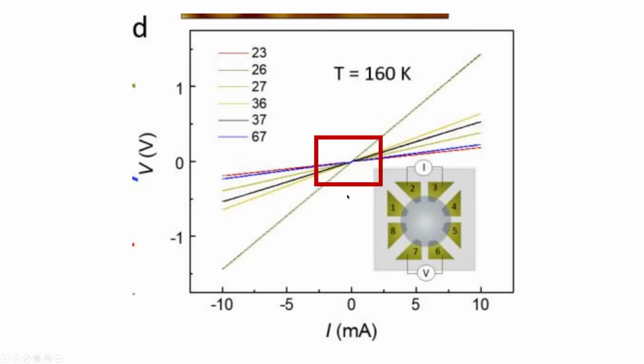And I'm going to zoom in even more. Of course, I can't keep zooming in because this is a rastered image of data. But I think you can see that basically there is this gap here between the positive side and the negative side, and this gap has units of about 50 millivolts. And my argument is that this is really basically what you would expect to see if there was some kind of barrier between the current carrying leads. And this was discussed in a post that my colleague and I had provided last year in August.